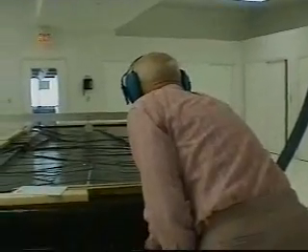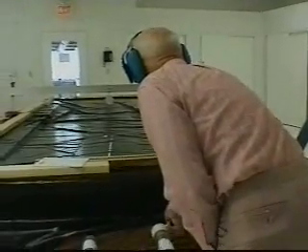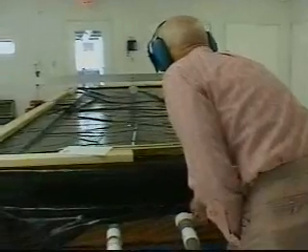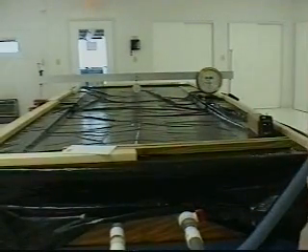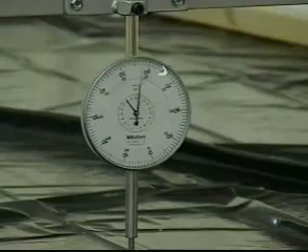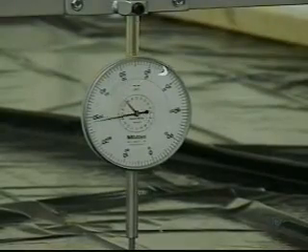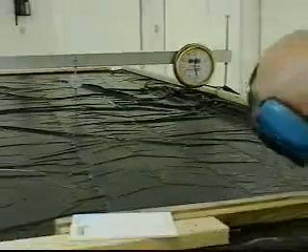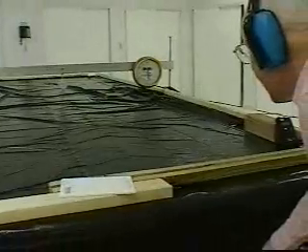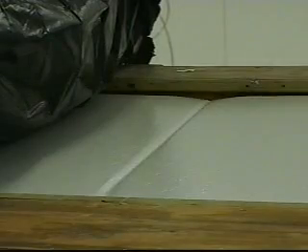The panels are also put through extensive and rigid testing to ensure they continue to meet or exceed building code requirements for wind, live and dead loads. The testing panel is placed into a vacuum tank and sealed with an airtight visqueen material. The air is slowly removed through the vacuum tank and the pressure is carefully measured. The time of failure determines the loads the panel can withstand.